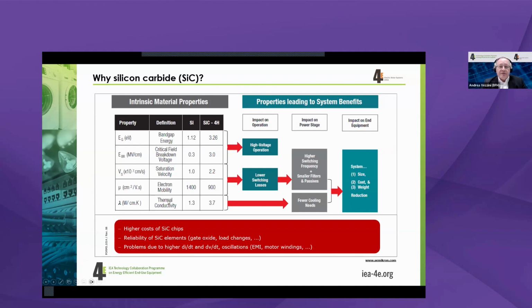bandgap energy or the critical field breakdown voltage, where you can see that silicon carbide outperforms silicon semiconductors by a factor of 3 to almost 10. And these two properties are basically responsible for the fact that you can operate silicon carbide semiconductors at much higher voltage. Very interesting, silicon carbide MOSFET starts at 1200 volt, but we also see 3.3 kilovolts, for very large power applications. So the impact is that these are very suitable semiconductor elements for high voltage operation.